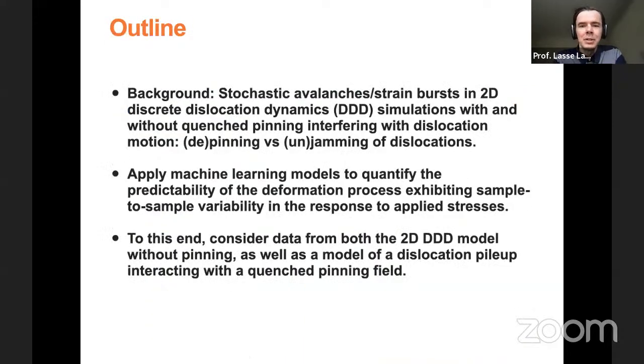So then the actual stuff. As I already briefly tried to explain, in plasticity, especially if you look at small crystals, what you will end up finding out is that when you slowly deform some small crystal, the way it deforms is that there are some avalanches or strain bursts of plastic activity, which seem to be hard to predict. I mean, it's stochastic and all this stuff. So it's a challenge to say, okay, if I have a specific microstructure in my crystal, how it will actually end up deforming when I apply some stress.